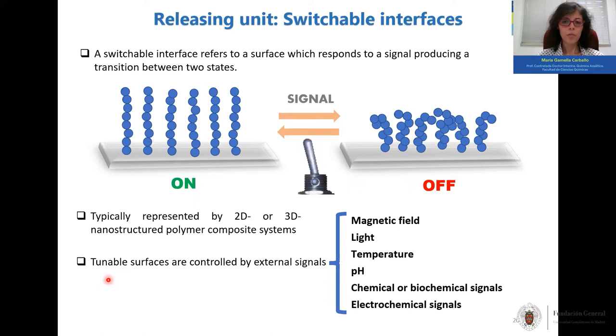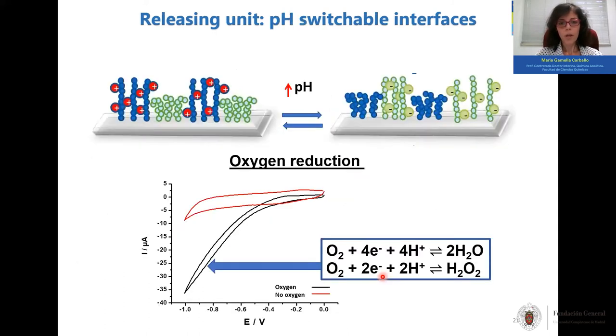These tunable surfaces can be controlled by different kinds of external signals such as magnetic field, light, temperature, pH, and so on. We specifically used pH switchable interfaces. We modified electrodes with two different kinds of polymers, making what we call polymeric brushes. These polymers present different structures at different pHs. The tool that we used to change this pH was the application of a negative potential. This negative potential produces a reduction of the oxygen in the media. As you can see on the slide, this reaction consumes the protons of the solution. Therefore, it produces an increase in the pH of the solution.